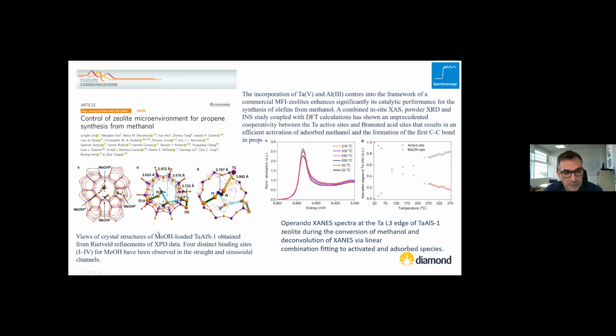In chemistry, there's a lot of work actually being done at the moment to try to understand how to improve catalysts. I don't think it's unique to Diamond. This is an activity, of course, which is pushed all over the world. This is a recent example of using commercial zeolite and trying to enhance its functionality by adding tantalum and aluminum to this host structure. And the reason I'm flagging this particular study is that what we're seeing more and more, and I think it's once again not unique to Diamond, but you can see that across the board, is the combination of different modalities when you do research like that, where scientists want to combine XAS, XRD, in this case, inelastic neutron scattering and DFT calculation, to actually understand how these materials, and these catalysts in this case, are improved when you modify their properties chemically or by other means.